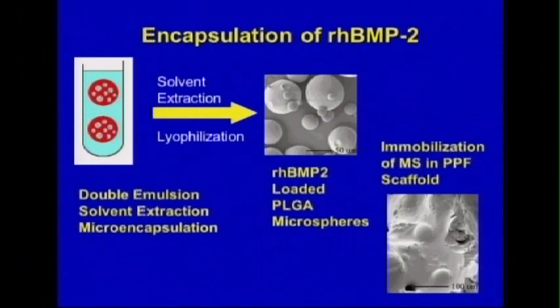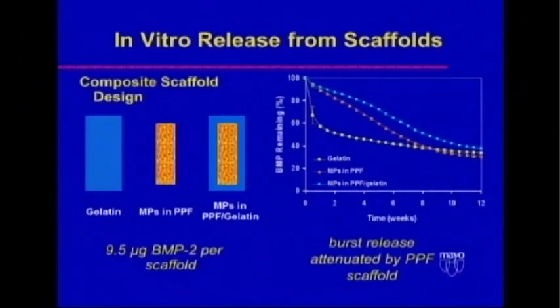So the diffusion path for the molecule is first to diffuse down a concentration gradient out of the microparticle and into the scaffold wall, and then to diffuse through the scaffold wall and into the pore. And thus, by choice of the nature of the microparticle, its composition, its molecular weight, its size, and the same thing for the wall, we can make a diffusion path that can have whatever we put in come out at a certain time and then hopefully act on whatever is in the pores of the scaffold.